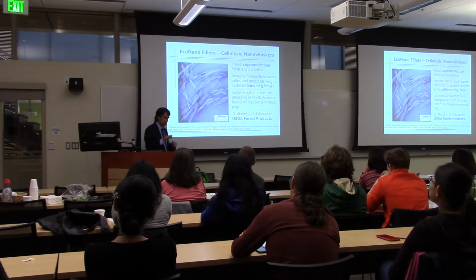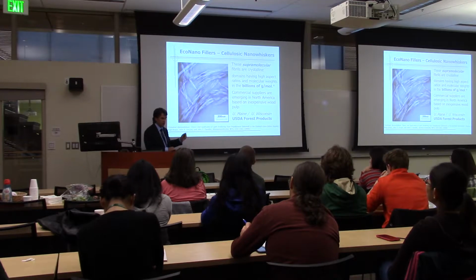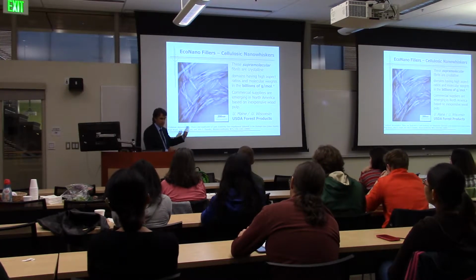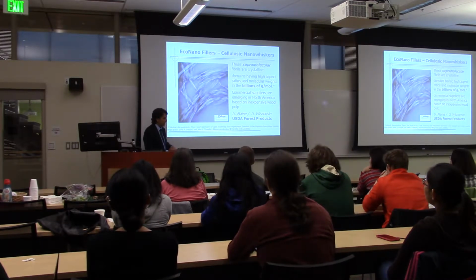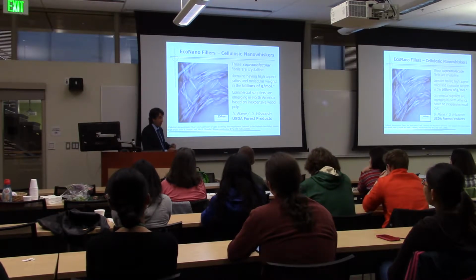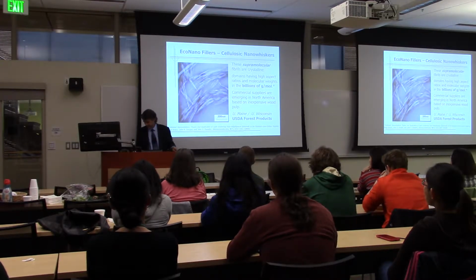I almost had a perfect answer for you, but unfortunately I was collaborating with Howard Fairbrother at Johns Hopkins University, and we had all these samples ready for biodegradable testing, and we killed his compost. We didn't make him very happy as a collaborator. And it turned out it was because the student had used mold release agent, and so he had sprayed Teflon on the mold before he made the samples, and so the fluorine got into the compost and made us unpopular at Johns Hopkins University. I haven't been invited there for seminar.